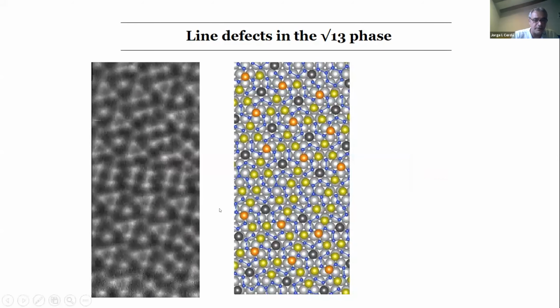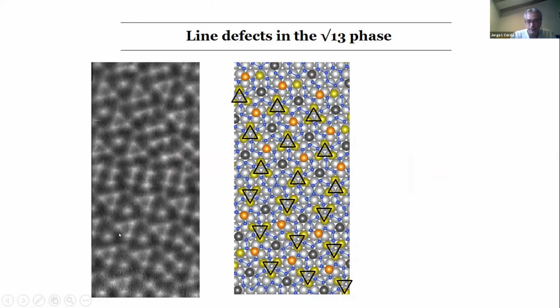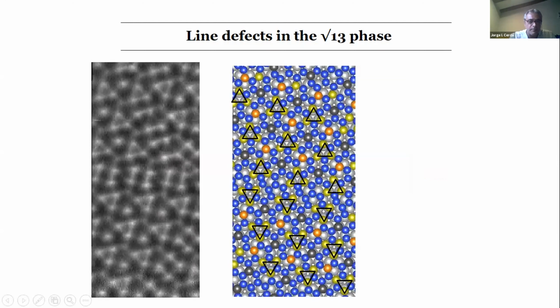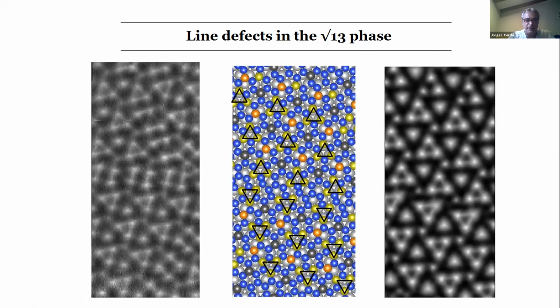To try to construct a model for this is a bit clumsy. We basically tried to place the atoms that we knew were bright, that would give us these signals on one side, also on the other, and try to fit the atoms in the middle, in the borderlines, and see what happens. This is just placing the triangles in accordance with a domain up and a domain down. And now we make bigger the rest of the silicon atoms, these blue balls, which would be the low-lying silicon atoms. Initially, without relaxing, this is what we get when we calculate the AFM image for this structure: a very abrupt interface between the two of them, with no signal of these ones.